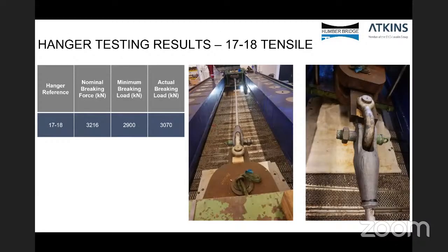This hanger, after it carried out the 2 million test cycles, was taken to be carried out for the ultimate tensile strength test. It was possible that during the fatigue testing, significant damage would have occurred to the hanger, and then when the ultimate tensile strength test occurred, we might get a significant reduction in the breakage. But what we found was that the actual breakage load was very similar to the previous at 3070, again greater than the minimum breaking load. So it was a positive result to prove that the hanger hadn't damaged during the fatigue testing. Look to the next slide, please.